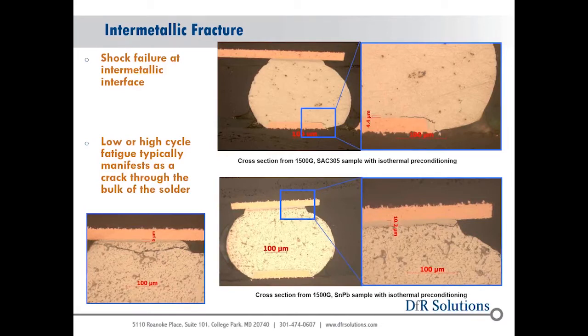Intermetallic fractures: it's a fracture through the intermetallic. They're typically an overstress. We wouldn't really see this during low cycle or high cycle fatigue. What we see with high cycle and low cycle fatigue are cracks in the bulk of the solder. So if you start to see cracks like this in the intermetallic on a unit and you try to convince yourself that this is vibration or low cycle fatigue, chances are it's not. It's somebody dropped the unit or did something to it.